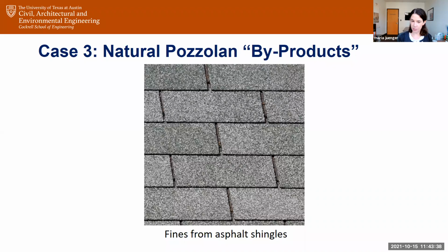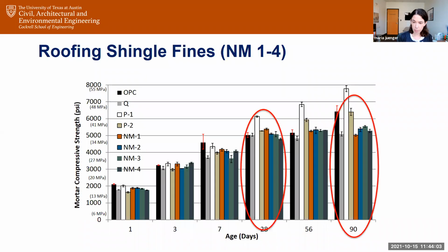So these fines, it's interesting, like we know from making concrete aggregates, if we're quarrying, say, a limestone aggregate, we know that we have to quarry it and crush it. And then in the process of crushing, we end up with a lot of fine material that we consider waste. The same for this sort of process, they're looking for a specific particle size range. So anything smaller than that is a waste byproduct of their industry. What's interesting about those is some of those particular aggregates have silica and alumina in them. And so they could presumably be really good supplementary cementitious materials.